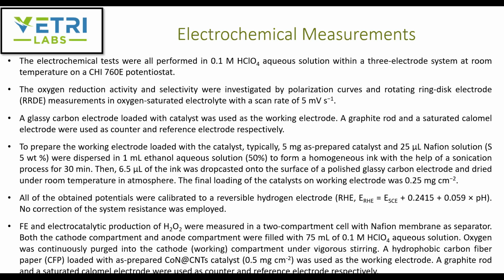And in later slides, they identified the concentration of peroxide, and the electrocatalytic production of peroxide was measured in a two compartment cell with a Nafion membrane as separator. They filled both the cathode and anode compartments with 75 milliliters of 0.1 molar perchloric acid, and they continuously purged oxygen into the cathode compartment. They used a hydrophobic carbon fiber paper loaded with the prepared cobalt nitrogen doped CNT catalyst, about 0.5 milligram per centimeter square, as the working electrode. The graphite rod was the counter, and saturated calomel was the reference electrode. And they calculated the concentration of peroxide by using potassium permanganate titration.